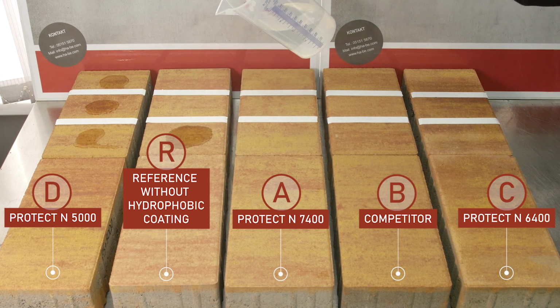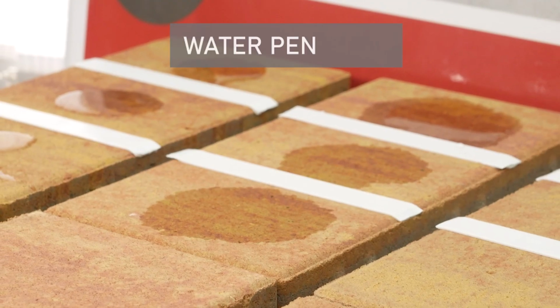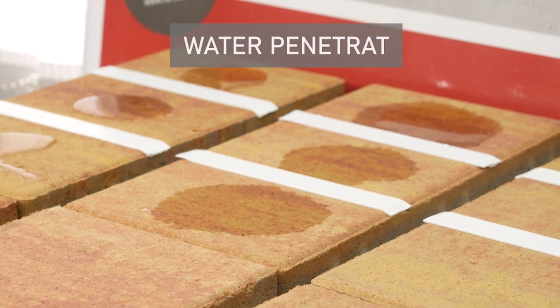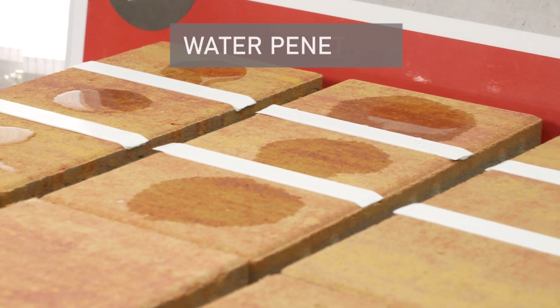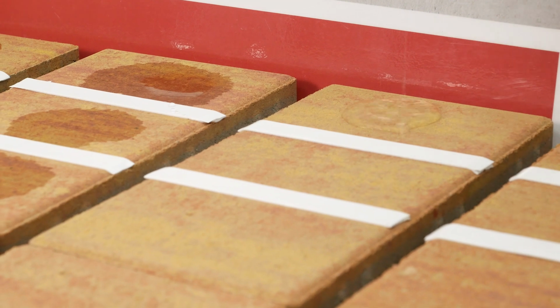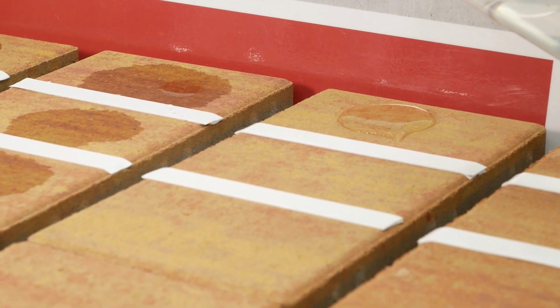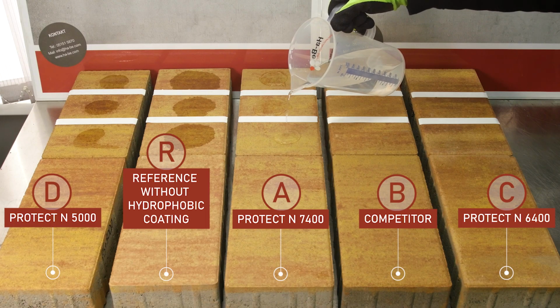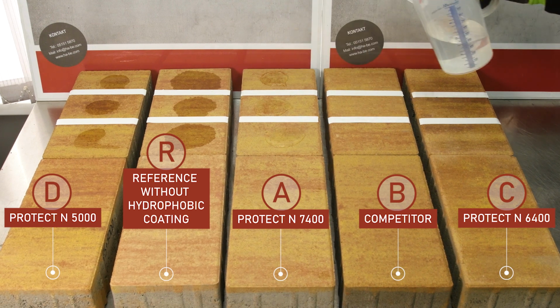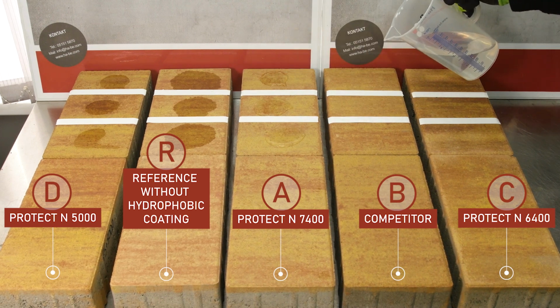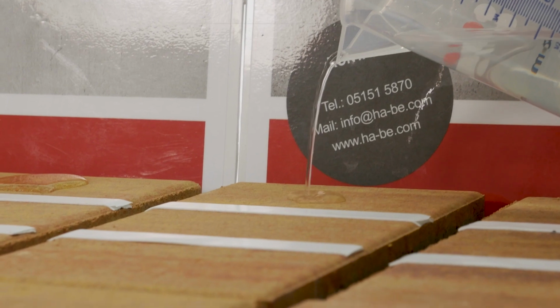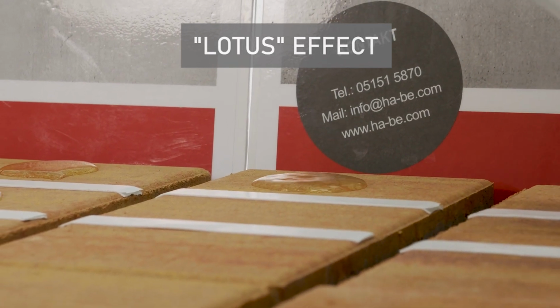With pouring sample 2 of the colour mix series, you can see how water immediately begins to penetrate into the substrate of the concrete. With pouring all samples of the colour mix series with a hydrophobic layer, samples 1, 3, 4, 5, you can see the effect of instant repulsion, the lotus effect.